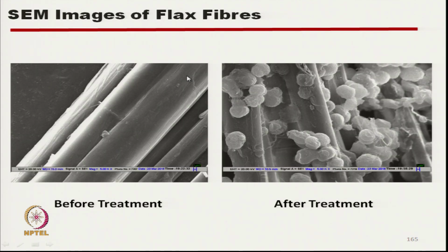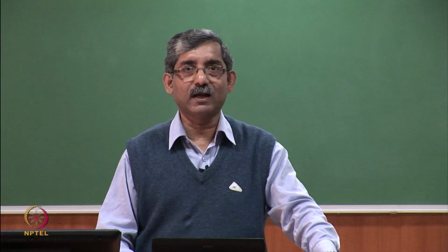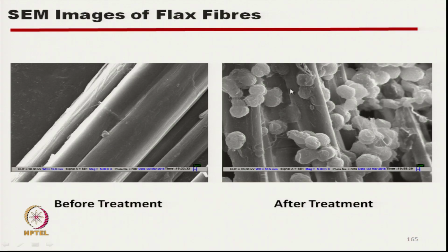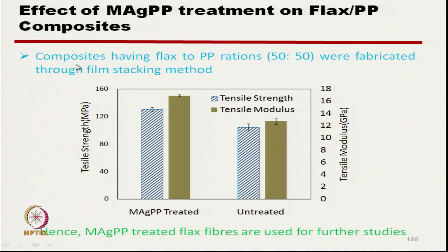If we see the flax fiber before surface treatment, there is no such chemical deposition, and these are the MAGPP. In fact, this MAGPP helps in proper binding with the polypropylene matrix, and we will see the characteristics without treatment and with treatment. With treatment we have seen significant improvement in properties.